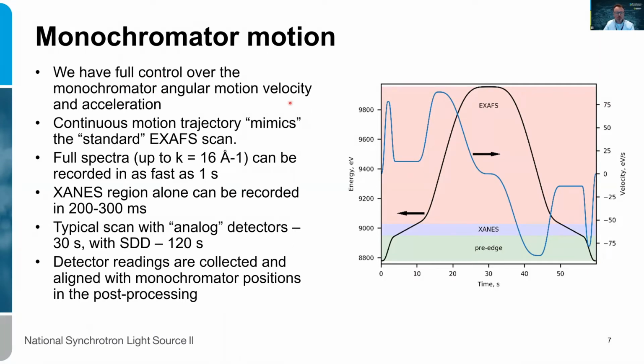volts. So there is one sort of unique thing about our ability to control the monochromator motion. We have full control over the velocity and acceleration, and we can simulate a traditional, so to speak, EXAFS scan, slowing down the mono and accelerating it when needed. So this is how we go through the regular EXAFS scan: fast through the pre-edge, slow through XANES, and then accelerating it again in the EXAFS range. And we can go both ways. So that really gives us good control over how we design the scan.